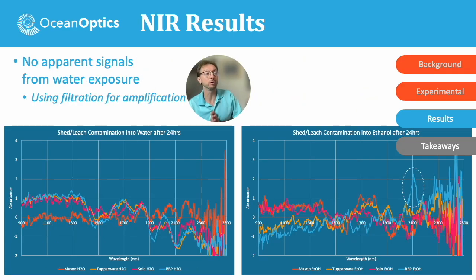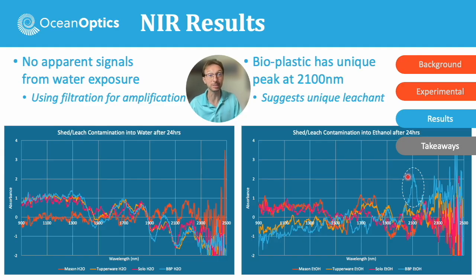With the near-infrared, there was no apparent signal when we did the water exposure, and I mentioned that it's inherently harder to get those near-infrared signals out of samples. So that's why we used that filtration to amplify and pump up whatever we could. We didn't see anything with the water, but we did get a nice peak up here from the bioplastic, right around 2100 nanometers. So we'll see if that does or doesn't show up in the bulk material. But that again suggests a unique leachant that's present, and it's interesting because it's strong enough to show up in the NIR, which means that it must be very pronounced for it to have this much of a signal in this kind of low activity region.